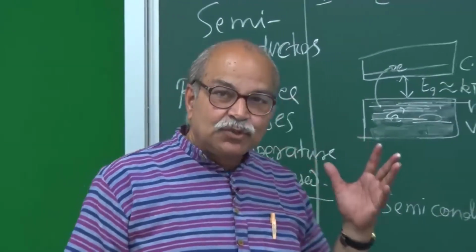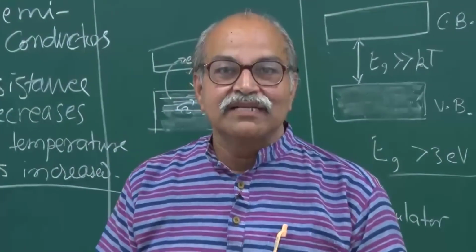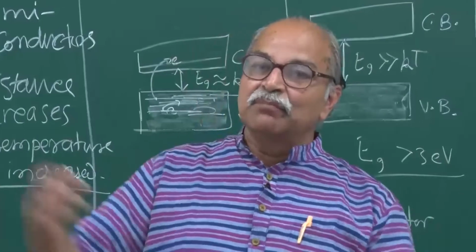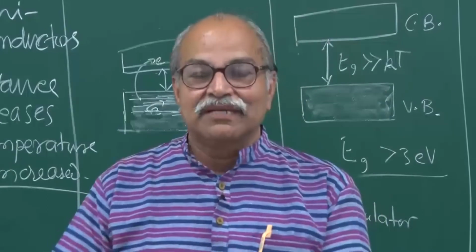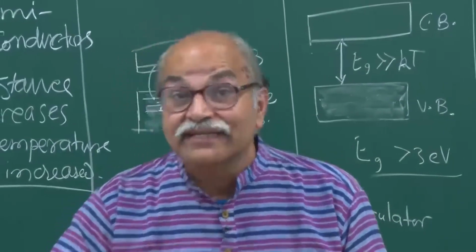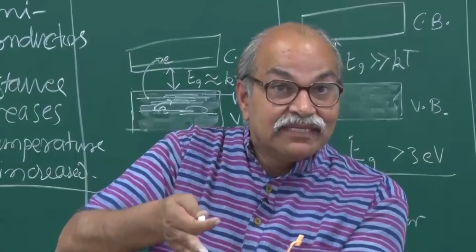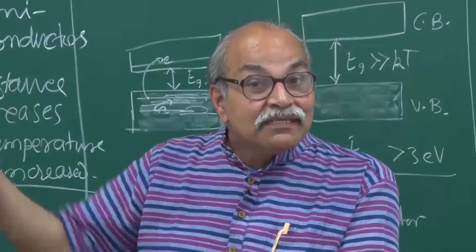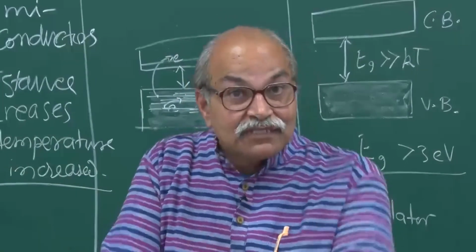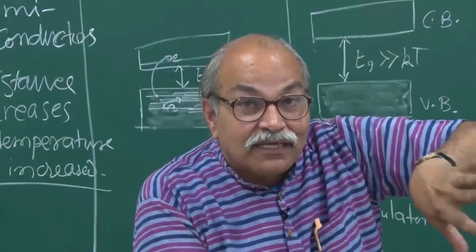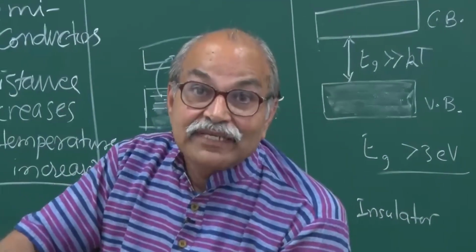This can be used to identify experimentally which material is a conductor and which material is a semiconductor, or if in some process there is a transition from metal to semiconductor or metal to insulator, going towards insulator. If there is some kind of transition, it can be identified experimentally by looking at the temperature dependence of the resistivity, and you can identify when it was in the conducting zone, and when it becomes semiconducting or insulating.